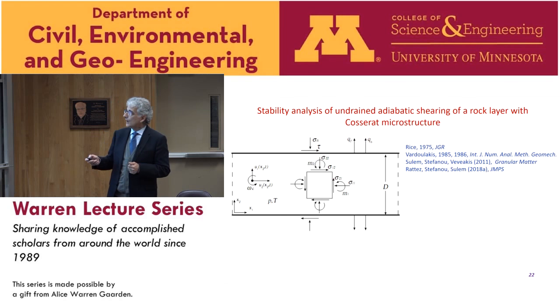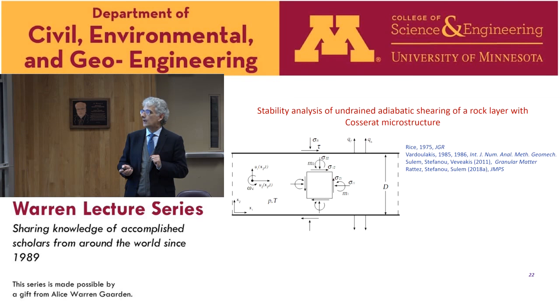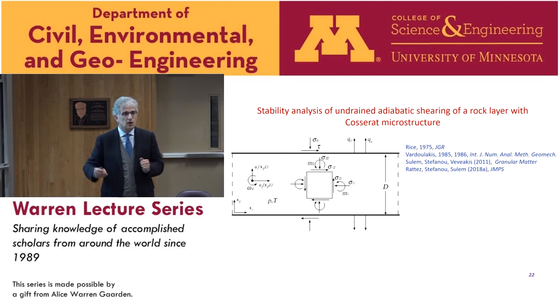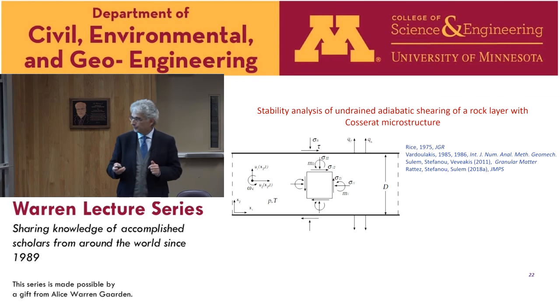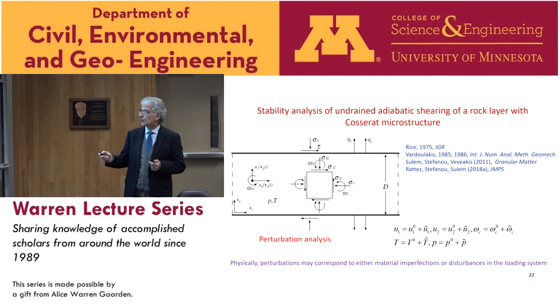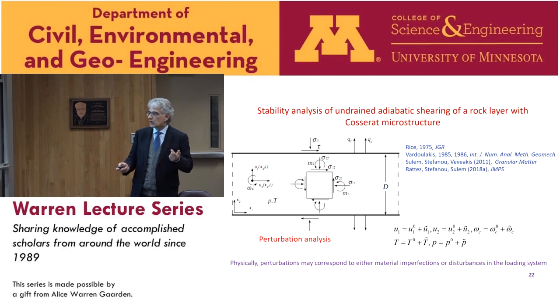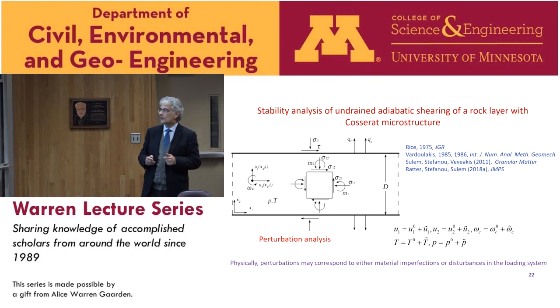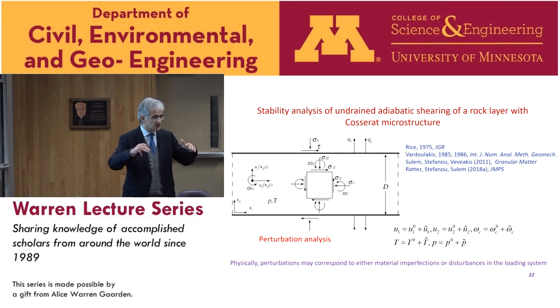Now in this problem, I consider a Cosserat structure, so I have to have the good limiters and the good description for the microstructure, but I will also consider the effect of temperature if we have a shear which is imposed at a very high velocity. So the technique, as proposed by Rice, is to perform a perturbation analysis of the homogeneous solution. Perturbations correspond to material imperfections or disturbances of the loading system. And we look at the evolution in time of this perturbation. They can vanish, which indicates that the system is stable, or they can blow up, which indicates that the system is unstable.